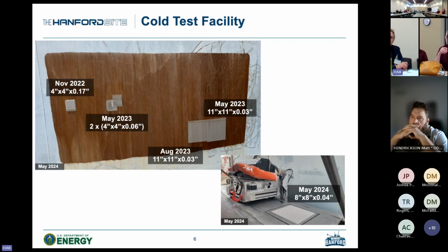That specific coupon was generated early in 2023. And so we have since performed some improvements on our powder feed selection and those material properties. So we have refined that surface finish to be a little bit smoother. And then this is the final slide. This shows the cold spray patches that were placed at the cold test facility.